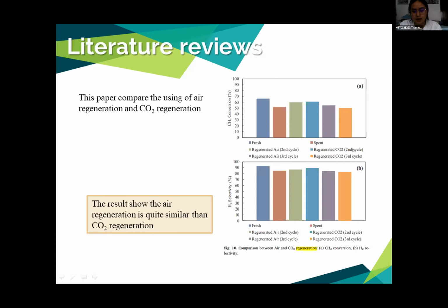This paper compares the coke removal between feeding air and CO2, and the results show that methane conversion and hydrogen selectivity are slightly decreased for the regenerated catalyst compared with the base catalyst. That shows the success of catalytic regeneration, and the result shows the air regeneration is quite similar to CO2 regeneration.